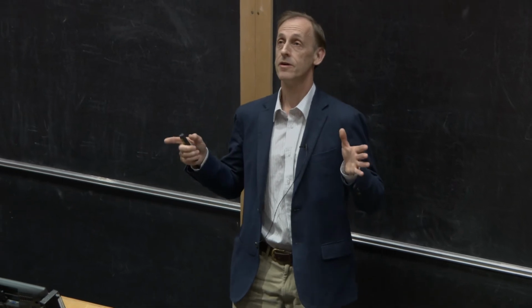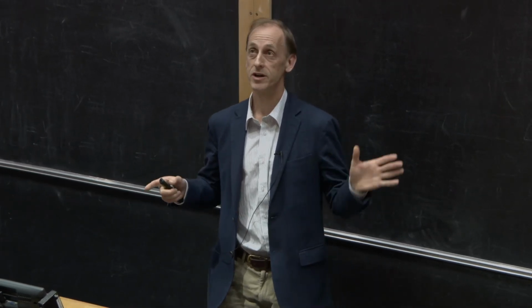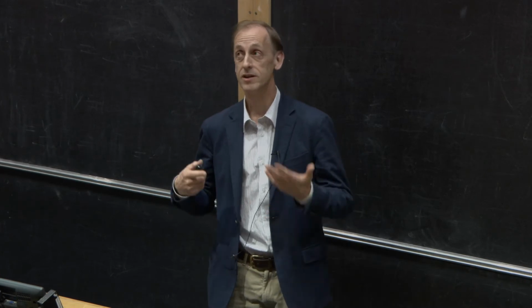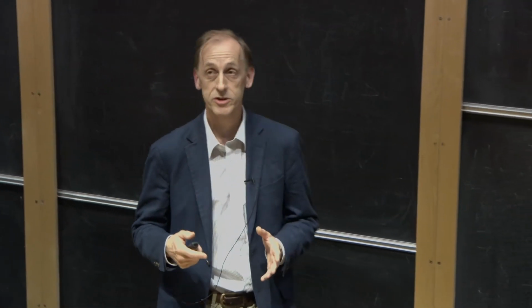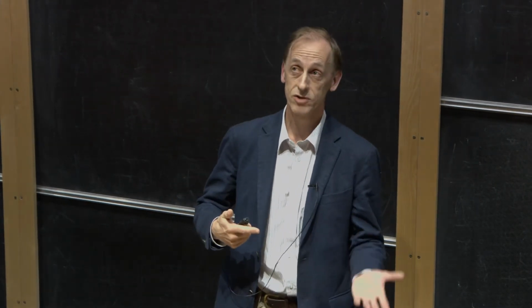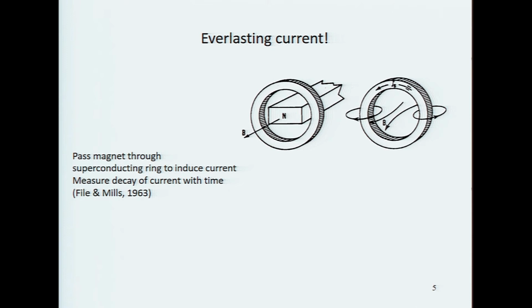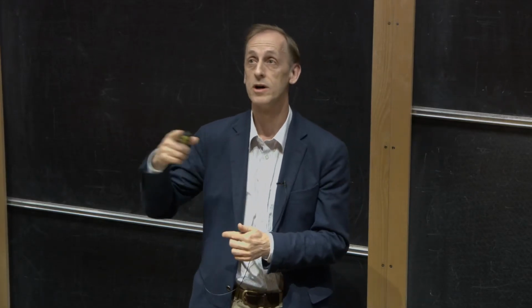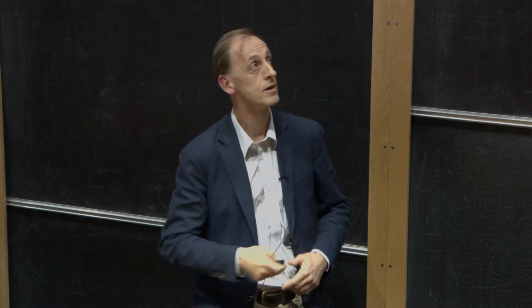Right, so Onnes realized or measured that the resistance of mercury and other metals went to very, very low values, but nobody really knew how low it was. And there were many experiments where people tried to measure how low the resistance really was after the metal went through this sharp superconducting transition. And one of the most celebrated experiments was done in the 60s by File and Mills. What they did was they made a ring out of a superconducting material. They cooled it down to very low temperatures so that it became superconducting, so it had a very low resistance. Then they passed a magnet through this ring, and this will induce a current in the ring just like the way a dynamo works. You pass a magnet through a coil, you get a current flowing in it.